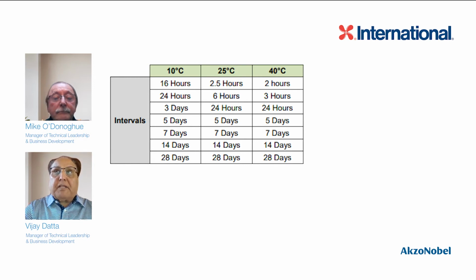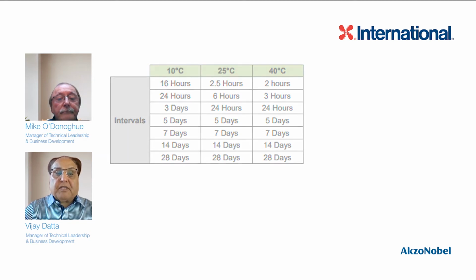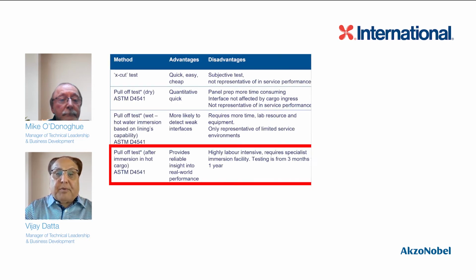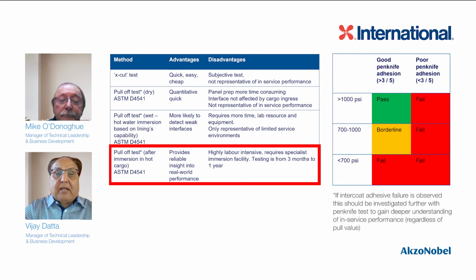We will spray the panels at different temperatures, cure it, and then we apply the second coat at different intervals, starting from 16 hours or 2 hours and going all the way to 28 days, depending on the temperature here. After that, we will immerse these coatings or panels into the various cargoes. We will have divided the cargoes into 2 categories.